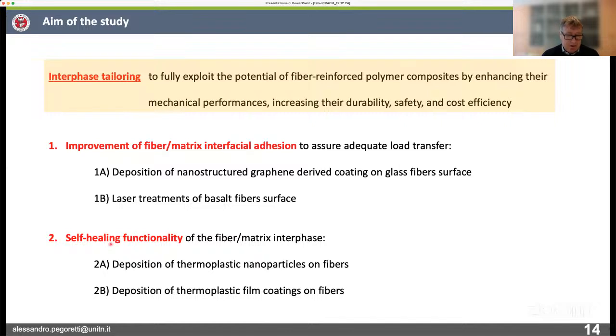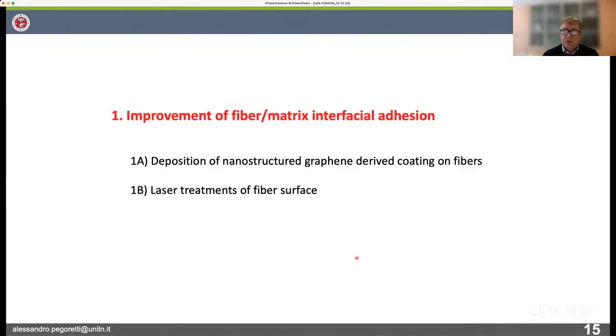Another area is, as I mentioned before, the possibility to repair somehow, to restore the initial mechanical properties after a debonding or a detachment of the fiber from the matrix due to a mechanical load. And in this area, we try to reach this in epoxy-based composite by depositing either thermoplastic nanoparticles on the fibers or a continuous film coating composed by a thermoplastic polymer on the surface of the fibers. And also in this case, these are very recent results that we published this year and also in 2024. And I will also share with you some of these results. So let's start from the first topic, which is improvement of fiber matrix interfacial adhesion.